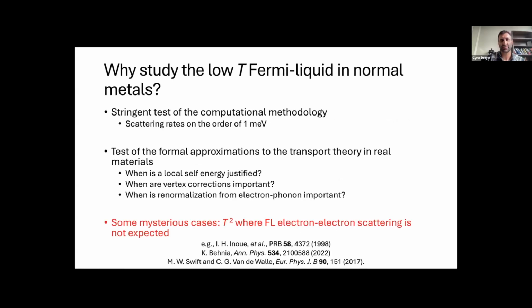Of course, you might ask, if you can't even observe this regime, why would we study it theoretically? I give three main reasons why we're interested. One reason is that these materials give a really stringent test of our computational methodology. Because of the very low magnitude of the scattering rates in high conductivity materials, it requires very fine convergence of numerical parameters to get accurate results.